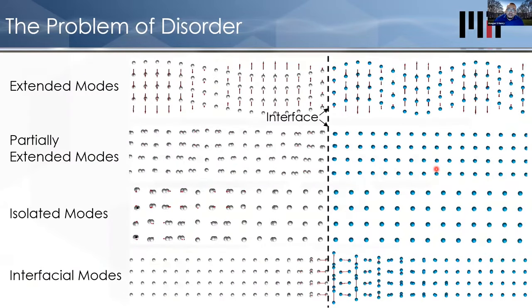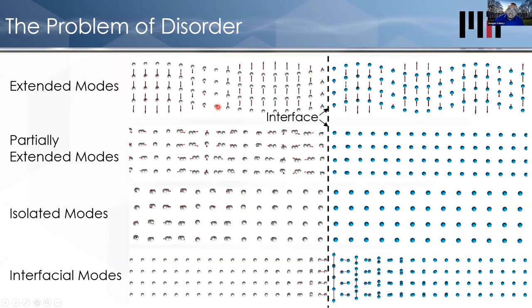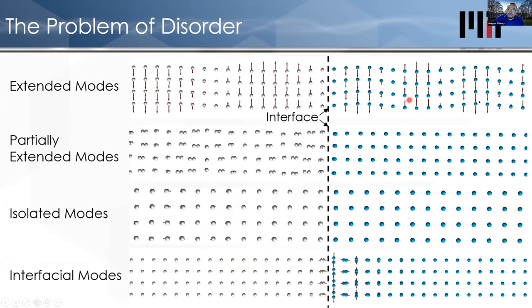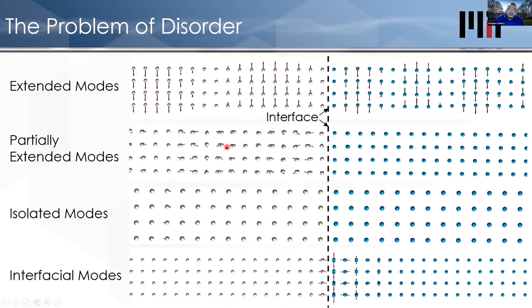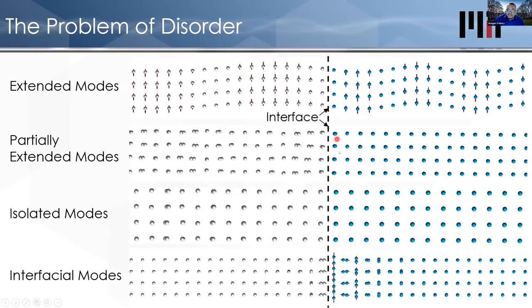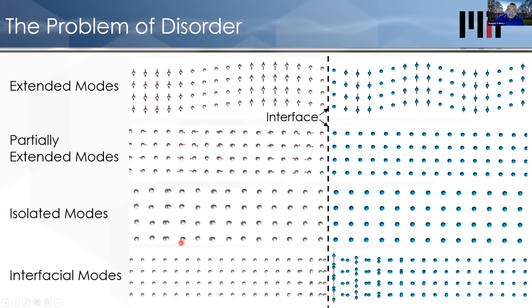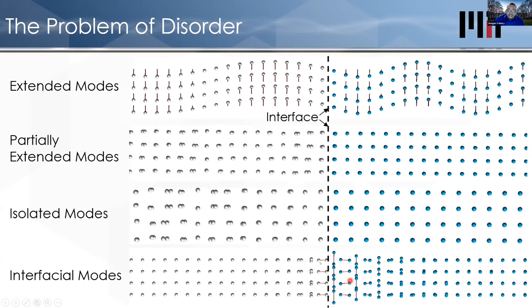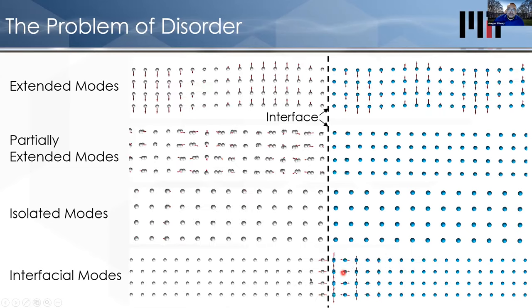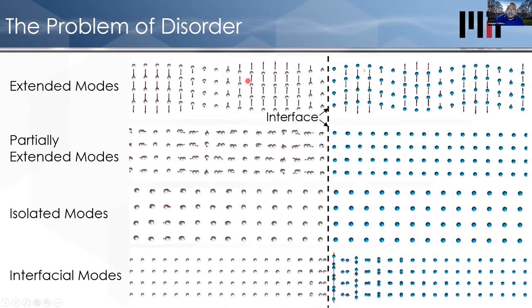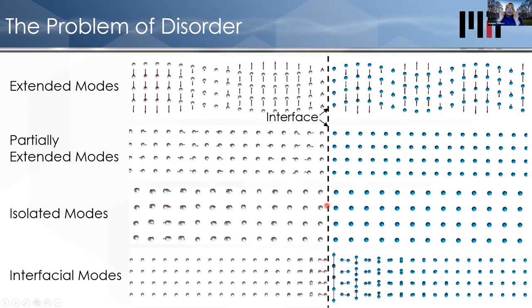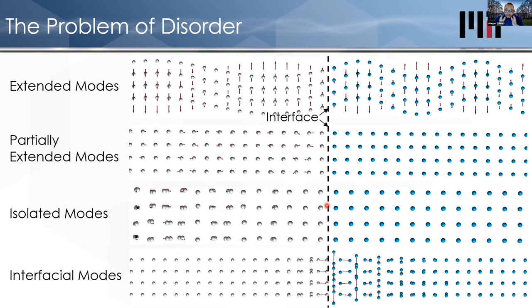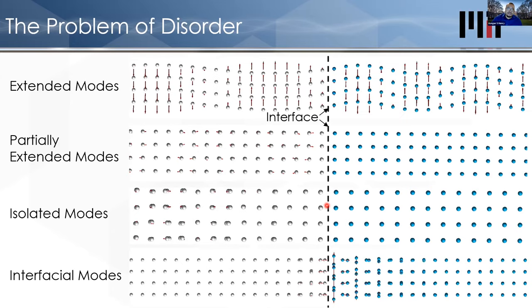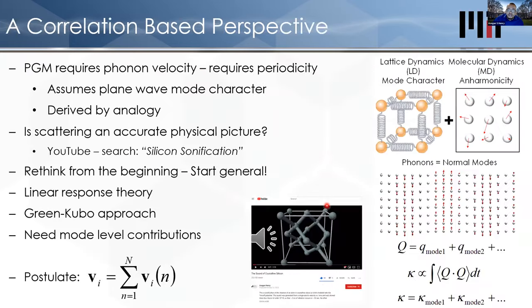When you now go to an interface, again, interesting things happen. You get some modes that actually extend through both materials, extended modes. You get some modes that actually stop at the interface and only go a little bit into the other side. Some modes are isolated on one side, and then you get localized modes right at the interface, which are called interfacial modes. So you get, again, new classifications of modes. They're not all plane waves. So now we have to diversify. We have to open up the physical picture to now be more inclusive of other types of behaviors other than just plane waves.